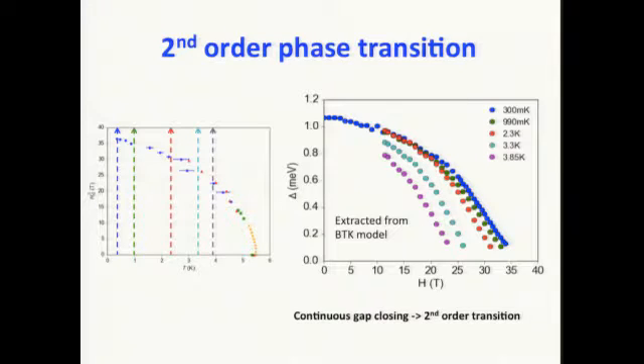We can fit our spectra with the BTK formula, actually developed at Harvard, at several different temperatures here. You can see that at all temperature scales, down to about 5% of the Tc, the phase transition looks like a second order phase transition in the whole phase diagram. So it's very different compared to a BCS superconductor.